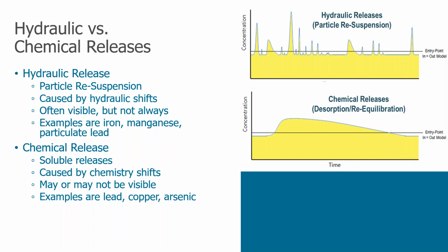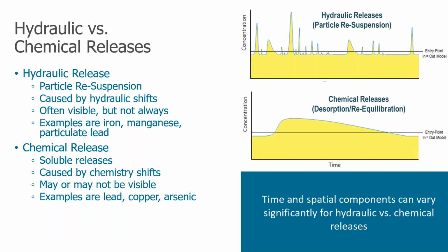And then with these hydraulic releases, these particle resuspensions that often have color to them and are releasing associated iron and manganese biofilm. But then when we have a chemical release event, the time scale can be much different. It can take days, weeks, months, or even years for scales to re-equilibrate. And the release may not always be in a visible form. When we talk about even just measuring lead and copper at the tap, those are release events that you really can't see. So it's important to note that these can be happening, and we're not always having discolored water along with it.